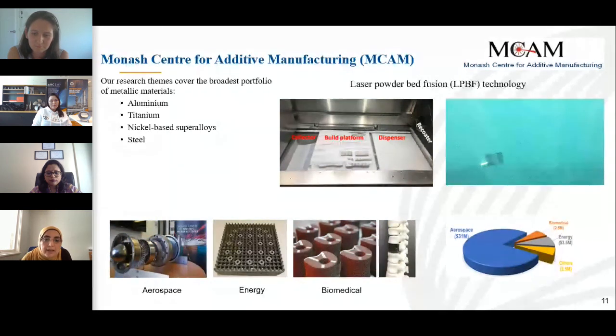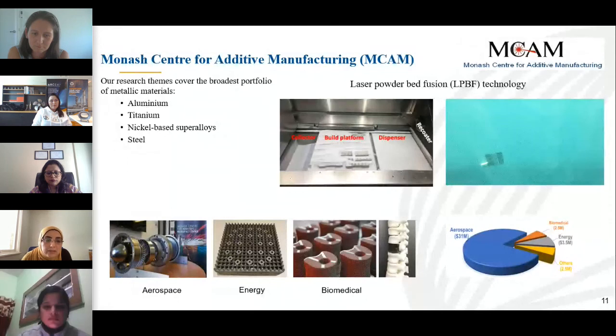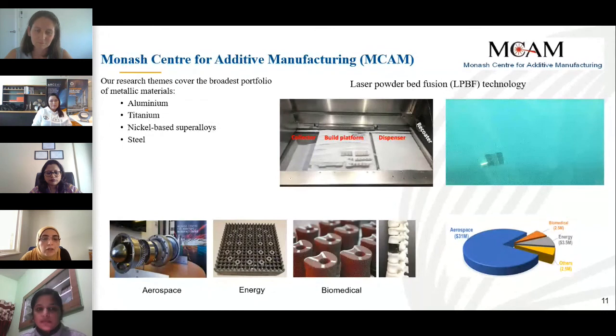That's why in our case, we developed a manganese-rich alloy compared to the magnesium-rich alloy. And we control the magnesium to be less than 1.5% in order to avoid the evaporation, because when the evaporation takes place, you end up with oxide inclusions in the material. You also might have some pores. So you cannot avoid this 100%, to answer the question.